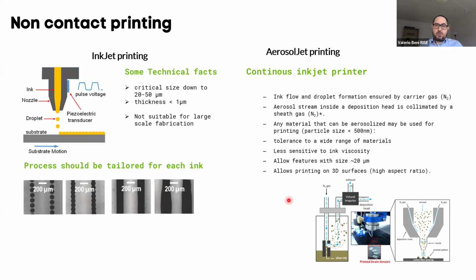Another very interesting and important feature of aerosol jet printing is that it allows you to build structures or to follow 3D structure patterns. So you will be able to print on substrates that are not fully flat, and that will allow you to look into more conformable electronics, or electronics that follow the shape of the surface. It was originally developed, for example, for interconnection of chips, so of bare die electronic chips. You could use this to contact the different parts on the chips, despite the fact that these are not flat compared with the original carrier.